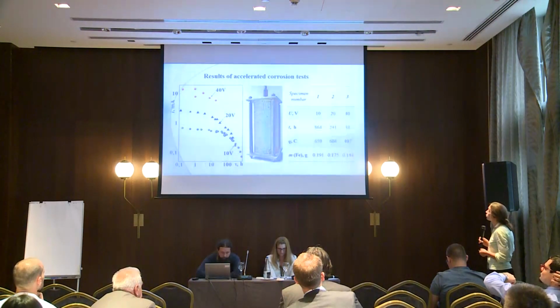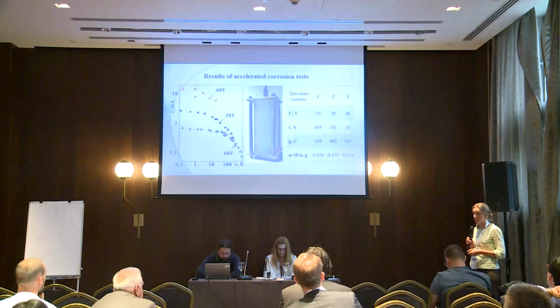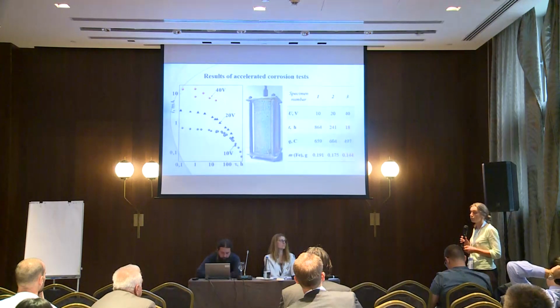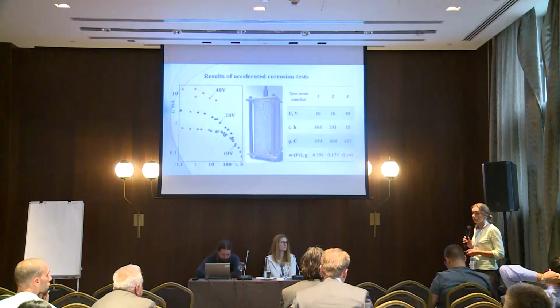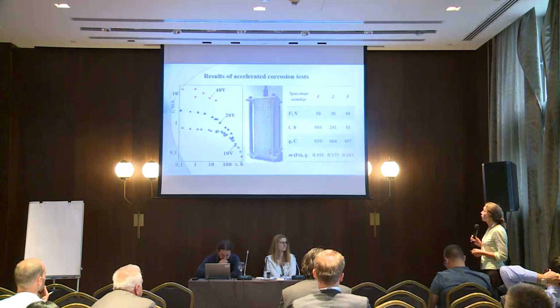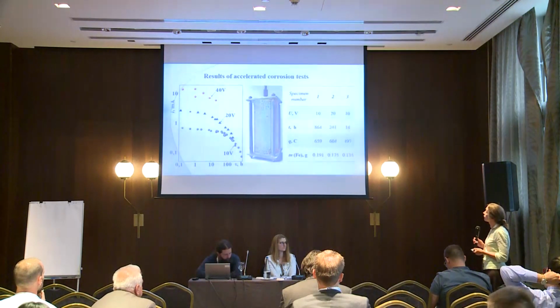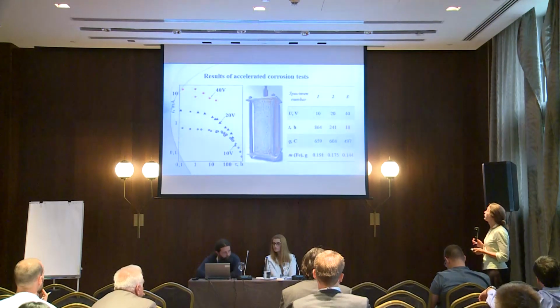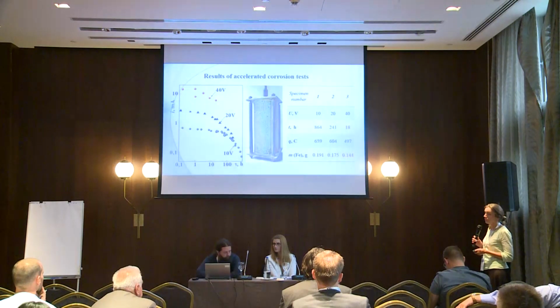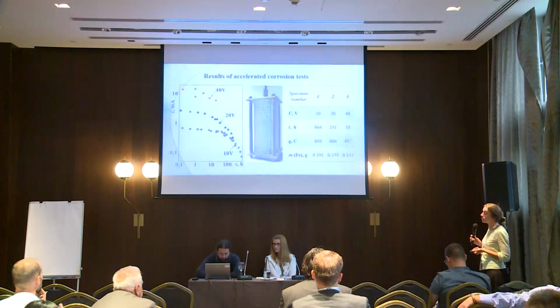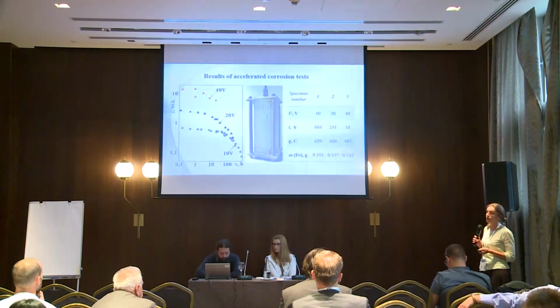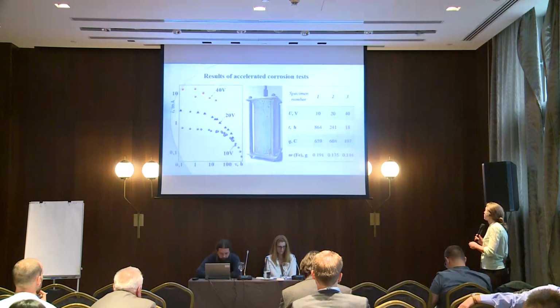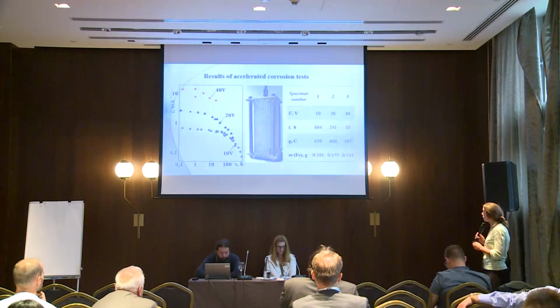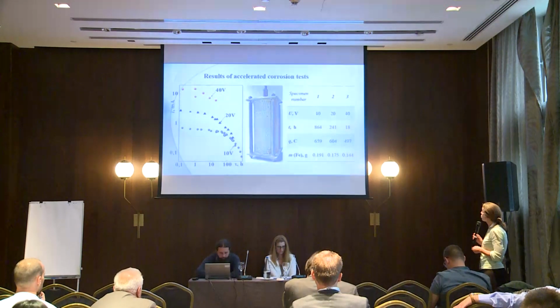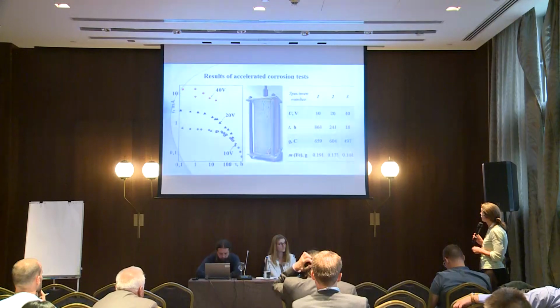It is known that not all corrosion products exert expanding pressure at the steel concrete interface. Some corrosion products can fill pores and defects in the near concrete layer, and some of these products can also migrate into the bulk of concrete. Evidently, under low corrosion rate, corrosion products have much time to penetrate into concrete, hence the critical pressure required for crack formation is attained under a larger amount of corrosion products, while under fast corrosion, the amount of corrosion products is low.